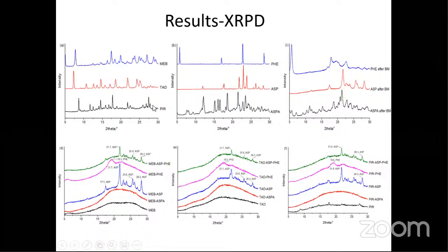So basically, from the XRD results, we can say mebendazole and tadalafil can become amorphous alone, but if you use aspartame, it can also be amorphous. And in the case of piroxicam, you have to use aspartame as a coformer because all the other samples failed to be amorphous except this one, right?